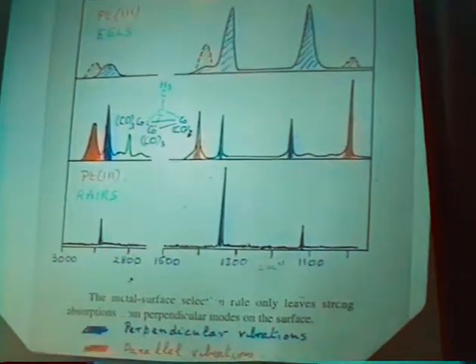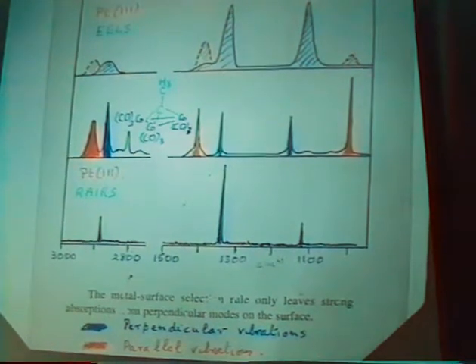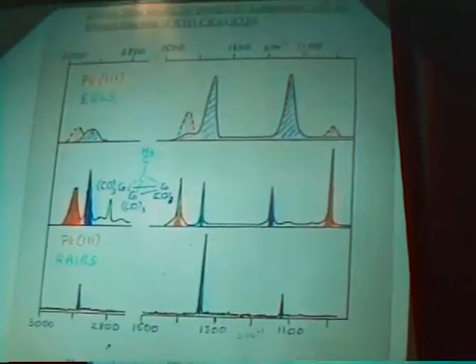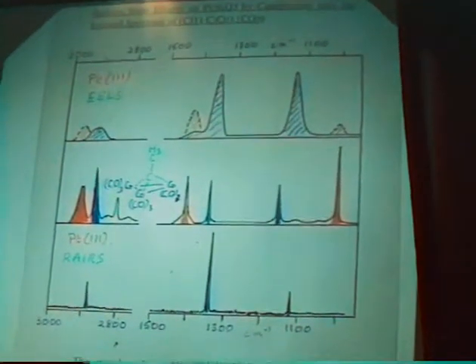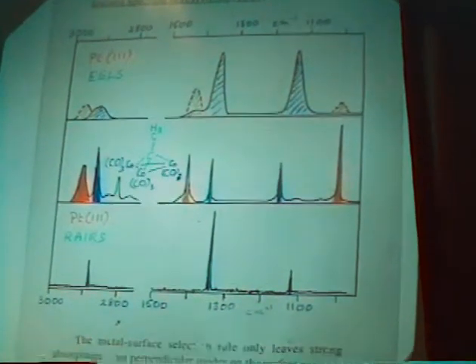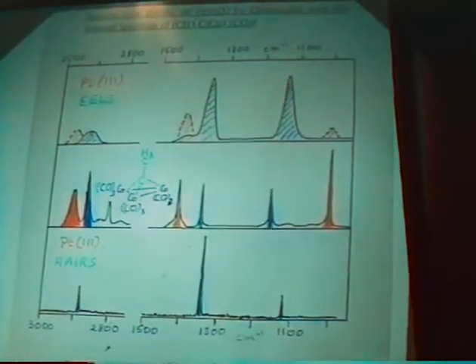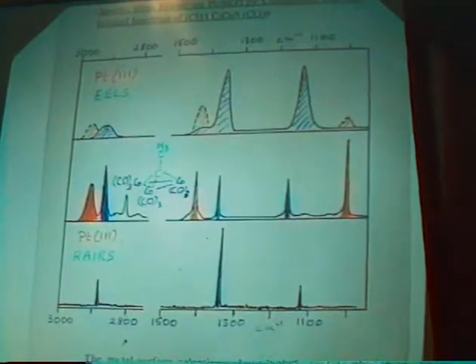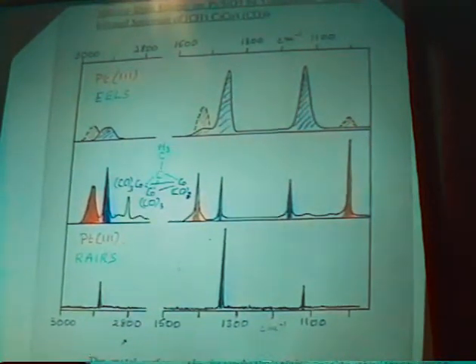In fact, I think Mike Chester's really surprised himself, because the bands are so much sharper than they look with the limited resolution of electron energy loss spectroscopy, that the signal to noise is even better than one might have expected. And there you have the ethylidyne species definitively defined. And at that time, I told you before, we had problems relating the strongest band here and here together. From then on, I believe, despite the CO experiment, they had to be from the same species.